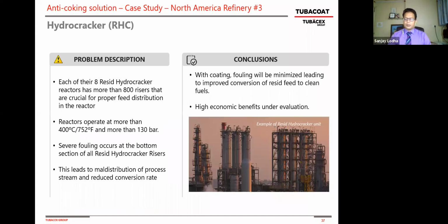This one is a Resid hydrocracker, again in North America. They have 8 Resid hydrocrackers feeding very heavy gas oil feed, and they have close to 800 risers. Those are used for the proper feed distribution in the reactor. Temperature close to 750 degrees Fahrenheit, 130 bar pressure, and due to the velocity regimes of the hydrocarbons, they have a severe fouling at the bottom section of the hydrocracker risers.